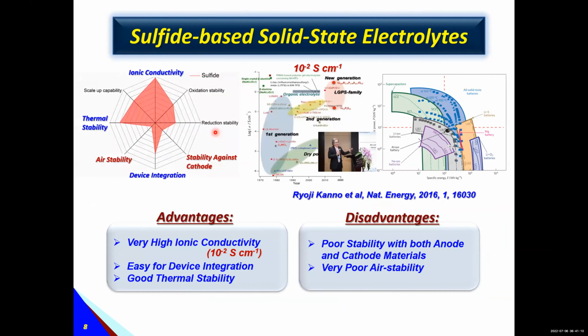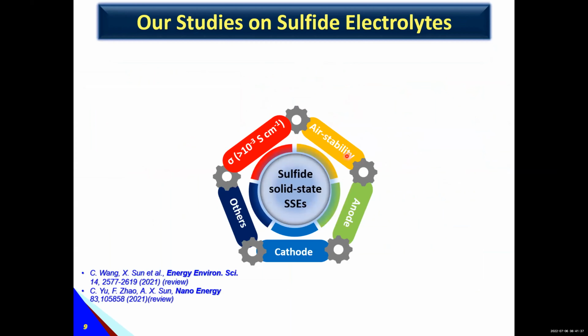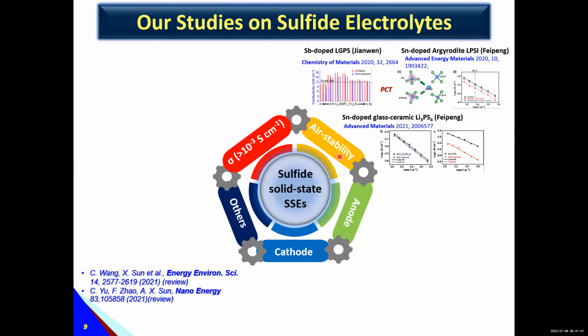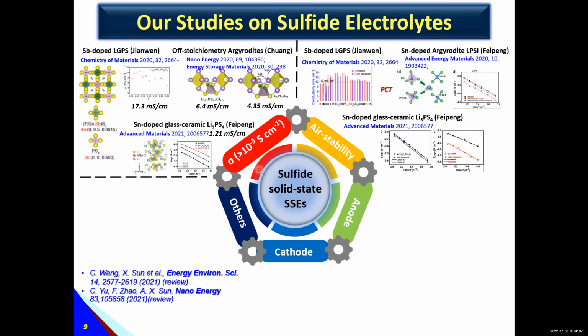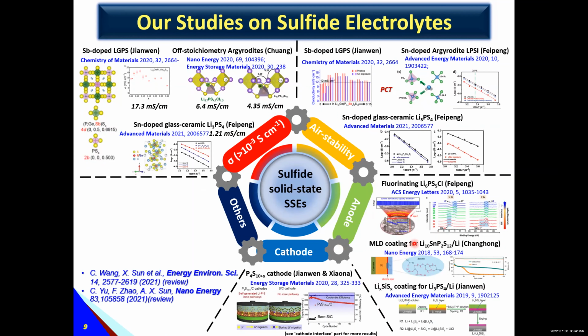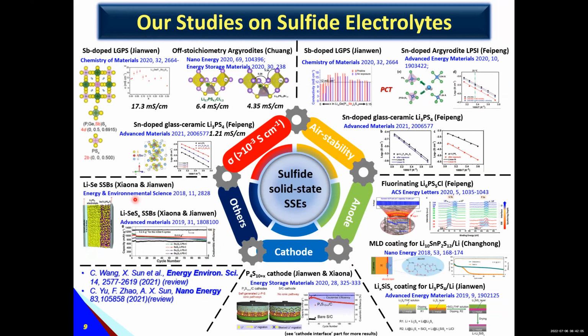I know many groups work on sulfide-based electrolyte, but we should see the pioneer is Professor Kanno. He worked on this for many years. There are several generations of sulfide-based electrolyte. The advantage is very high ionic conductivity, but they have challenges: air stability and also reactions with the cathode and anode. So that's why all groups work on this material, from synthesis, for example trying to control air stability and the structure, maintaining good ionic conductivity, and also anode and cathode interface control, for example doping with fluoride, or using MLD and ALD coating. We also demonstrate systems like lithium-sulfur and lithium-selenium. But now I just focus on the interface with the cathode.